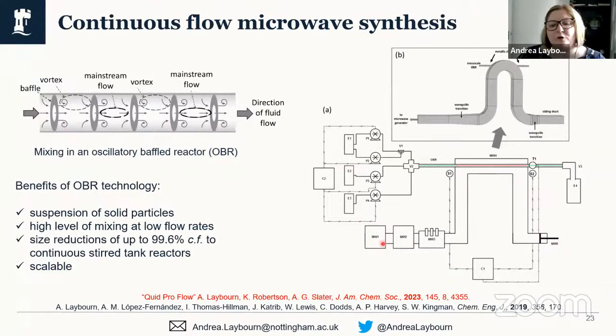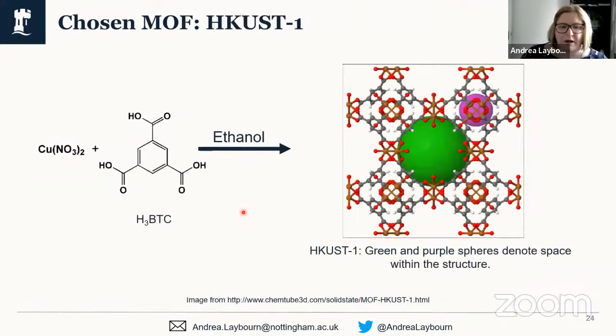And again, we have the peripheral equipment and the hardware to be able to look at the absorbed energy and the absorbed power. The MOF that we chose to have a look at in this particular case was HKUST-1, which can be synthesized from copper salt. So in our case, we were looking at copper nitrate. You then react this with the trimesic acid linker. In our case, again, in keeping with the sustainability drivers, we had a look at synthesizing this in ethanol. And this produces the HKUST-1 structure, which is shown here, where you have copper paddle wheels with your trimesic acid linkers in these positions, and you've got two areas of pores, or two different pore sizes within this material.